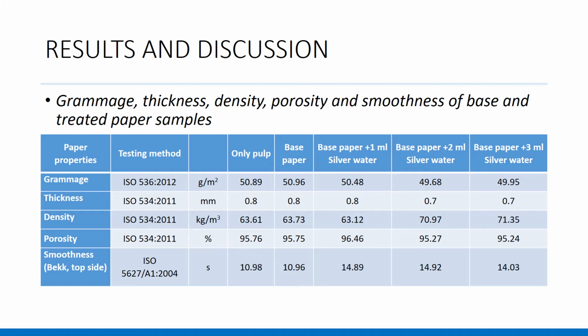Regarding the samples treated with silver water, an increase in the smoothness of the paper was observed, and as the amount of the silver water increased, the effect decreased. As expected, the thickness of the samples had mostly the same values, with a slight decrease at paper samples treated with 2 and 3 milliliters silver water. These results are based on the additional moistening of the paper with silver water solution and its subsequent drying on the sheet making machine at 96 degrees Celsius for 5 minutes.